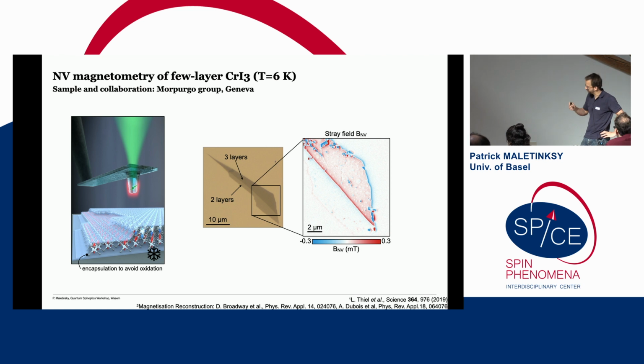So here is just to flash the results from that time. This is one of the samples that Alberto and colleagues prepared for us. This is chromium triiodide, a bilayer and a trilayer flake. I should stress, and this is illustrated here, that those are extremely fragile samples. They essentially self-destroy immediately under atmosphere, so you need to encapsulate them very carefully so that they remain intact. Once we had these, we put them into our system. Incidentally, these materials order at rather low temperatures, in this case at 40 Kelvin. So we brought this into our cryogenic scanning NV magnetometer and performed imaging.